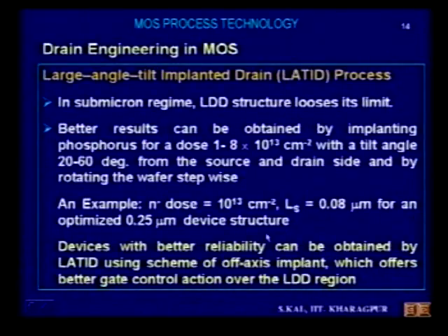There the oxide spacer length is 0.08 micron, and the lightly doped region below that is also 0.08 micron. Devices with better reliability can be obtained by LATID using a scheme of off-axis implant, which offers better gate control action over the LDD region. LATID offers better gate control action over the LDD region.